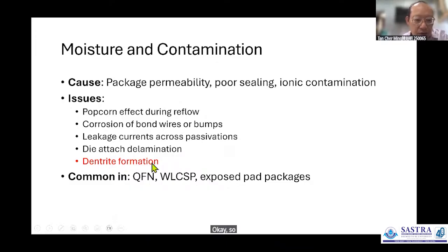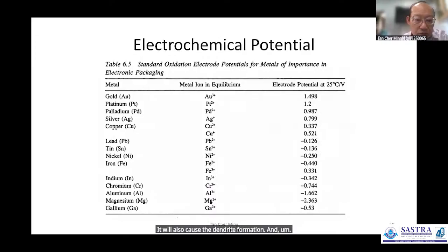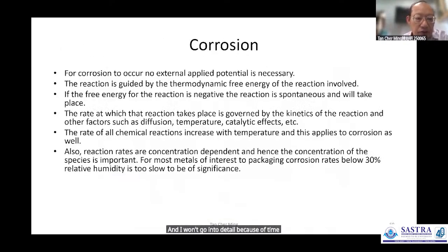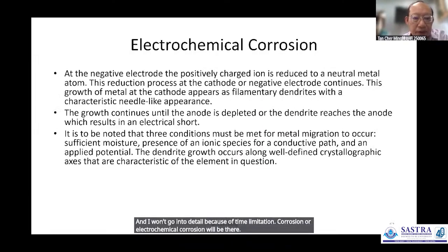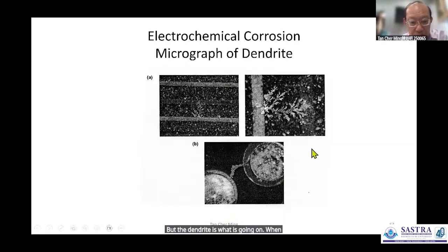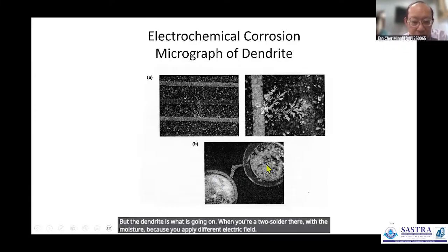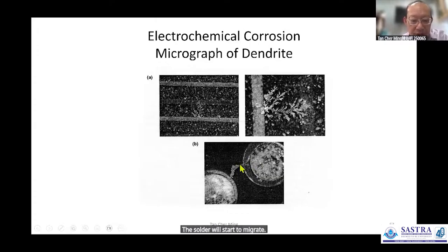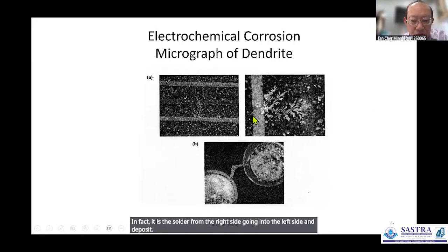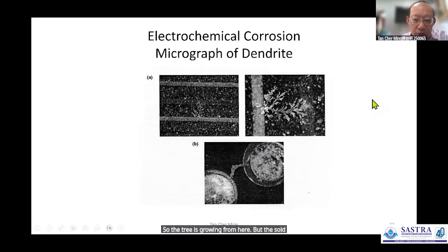Furthermore, when moisture gets in between the solder bumps, it will also cause dendrite formation. And then there's corrosion, and I won't go into detail because of time limitation. Electrochemical corrosion will be there. But the dendrite is what is going on. When you have two solders there with moisture, because you apply a different electric field, the solder will start to migrate in the moisture from anode to cathode, and in the end, a short circuit. So this is the SEM picture of the dendrite growth. In fact, it is the solder from the right side going into the left side and depositing. So the tree is growing from here, but the solder is actually moving from the right side to the left side. And this is causing a short circuit.